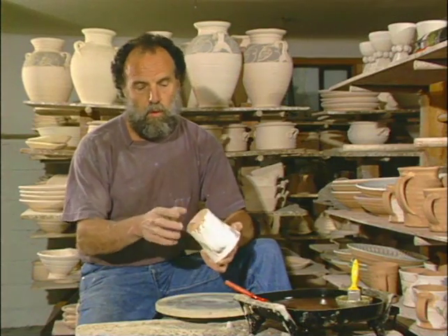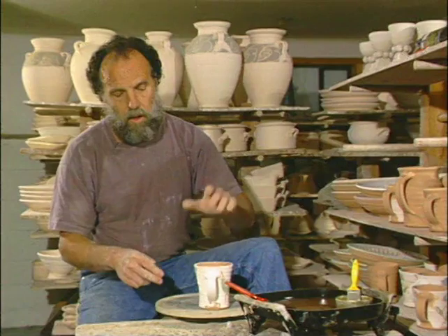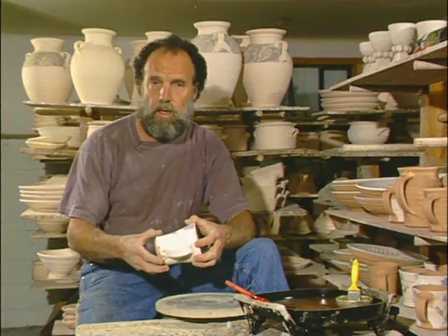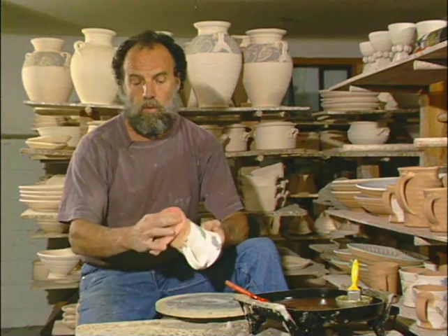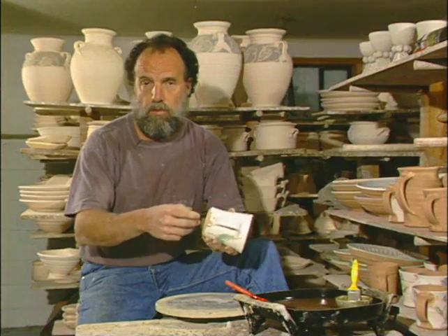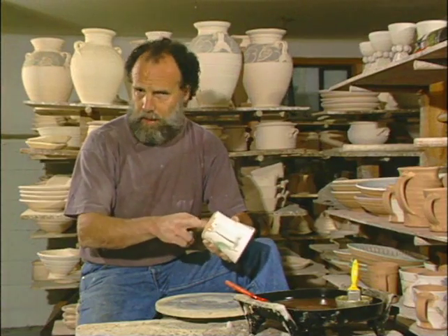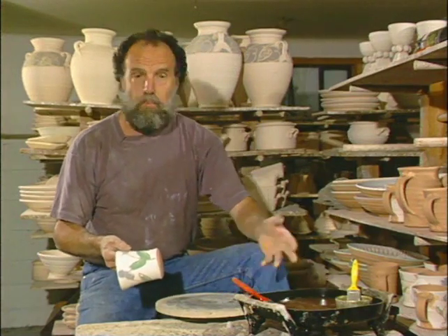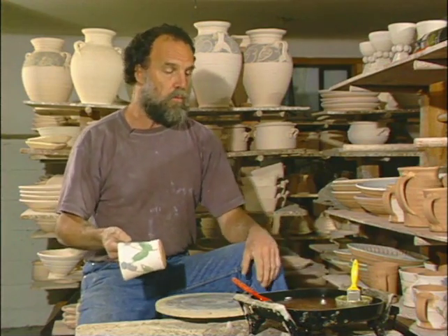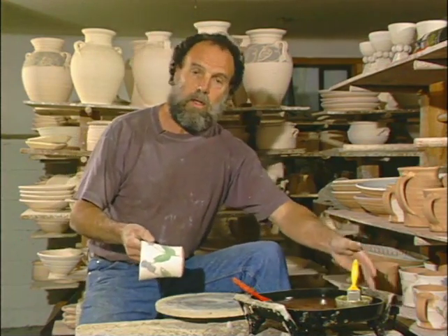So you've got to make sure that when you glaze the pot, there's no glaze where it touches the shelf. Now, you can ensure that by being careful when you glaze, and perhaps anything that does get on, you can wipe it off with a damp sponge. Or you can exclude glaze from it by using a commercial wax emulsion that you can buy from your ceramic suppliers. Or you can do what I prefer to do, and that's to use paraffin wax in an electric frying pan. Now, this is just regular paraffin that you'd use in canning, available in the supermarket or the ceramic suppliers, and a regular electric fry pan set at a medium temperature.